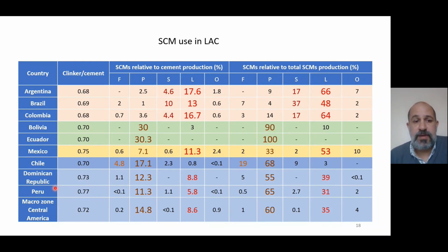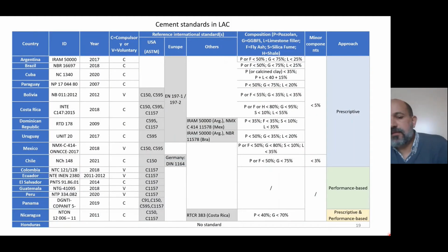And then we have Peru and most of the countries in Central America, where the most used SCM is natural pozzolan, but also a significant amount of limestone is used. So we can divide the region in several groups in which limestone, slag, and natural pozzolans are the dominant SCMs. This is based not only on the geography of the different countries, but also on the specific productive structure, whether they have a steel industry or not.